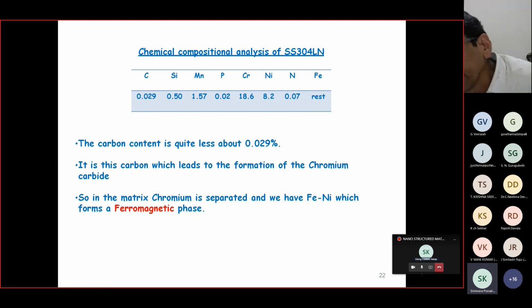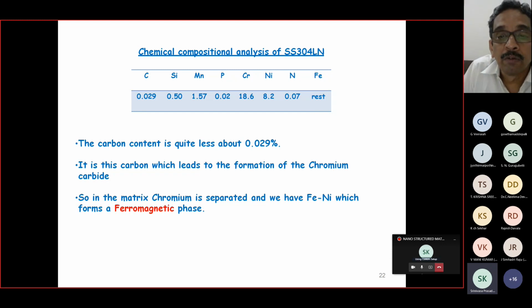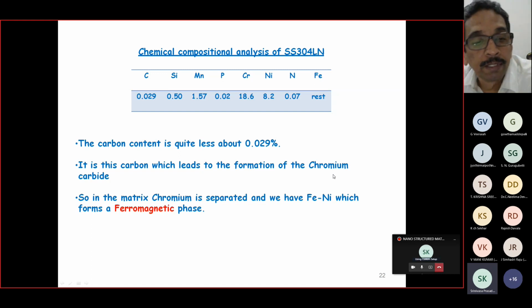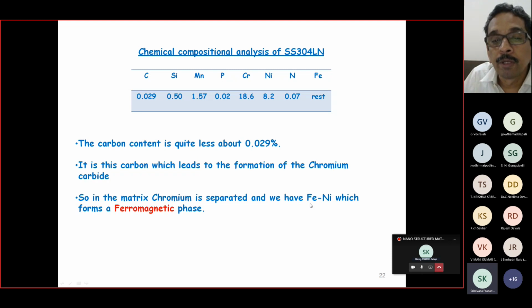Why low carbon? Because when this particular stainless steel 304 LN is used for applications at high temperatures, this carbon forms what is known as chromium carbide. And chromium carbide is very brittle in nature. I'll show you in the next slides how brittle it is. That means the chromium is separated from the matrix and we have iron and nickel. Okay. So then, iron and nickel form a ferromagnetic phase.